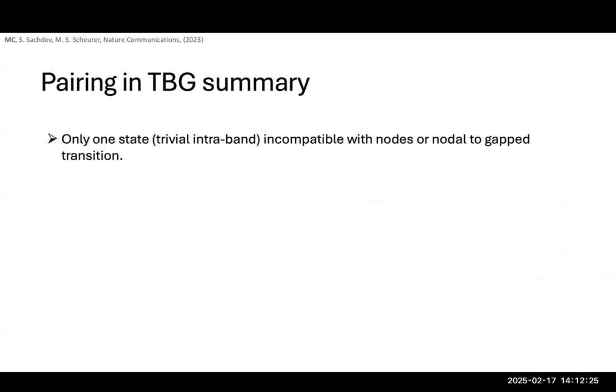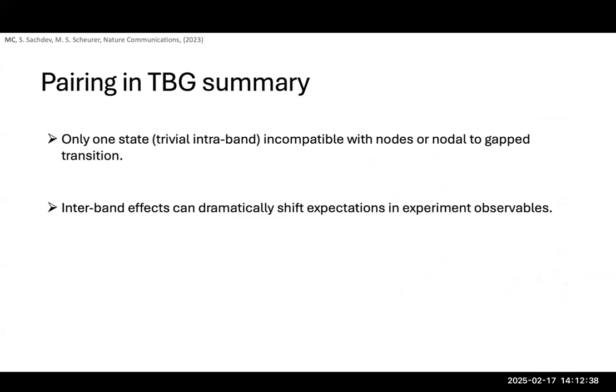So to give a summary of all of this in TBG, there's only one state, which is this trivial interband state, which is incompatible with nodes or nodal to gapped transition, and that interband effects can dramatically shift your expectations for different experimental observables.